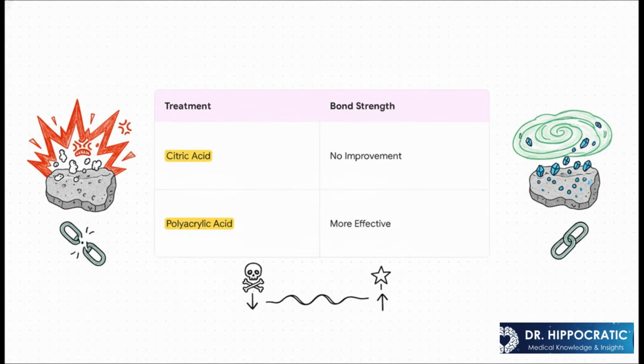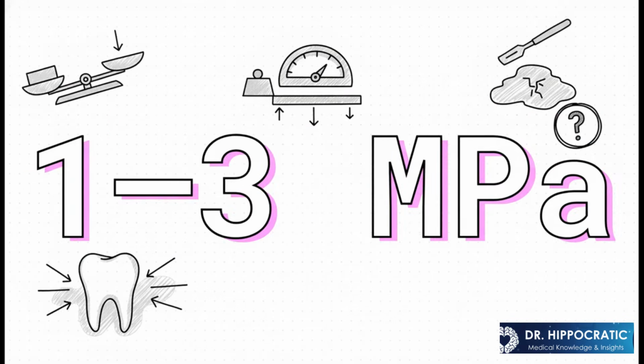Now, how you clean that surface is absolutely crucial. If you use something too aggressive, like citric acid, it's kind of like using heavy-duty sandpaper when you just needed a damp cloth. Sure, it gets rid of the smear layer, but it also damages the dentine itself by stripping away the calcium. And here's the kicker. The glass ionomer needs that calcium to create its chemical bond. So the harsh acid literally removes the very thing the glue needs to grab onto. The much better approach is using a gentler conditioner like polyacrylic acid. It just modifies the surface enough, leaving the calcium right where it needs to be, ready for a good, solid bond.